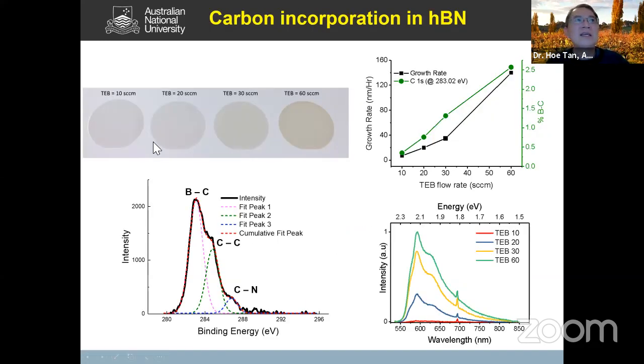And secondly, what we studied is, you can see here, these are 2-inch wafers of sapphire that we grow HBN on. So this is a very low flow of boron source. Okay, as you increase the amount of boron flow, you can see the film becomes darker. Okay, so what we actually found out is that the color from this film actually comes from the impurity. And because triethyl boron has got a lot of carbon, we identified that this coloration is due to the carbon impurities from the source. Okay, so if you measure the optical properties, you can see there's some emission coming out in the visible region.